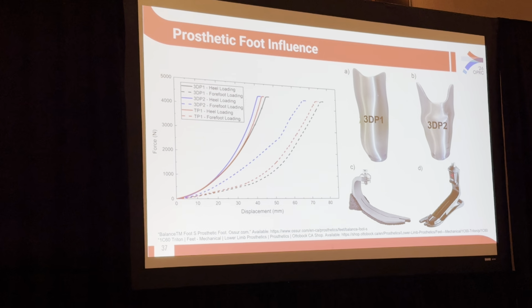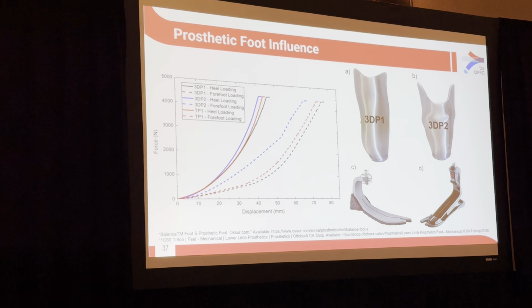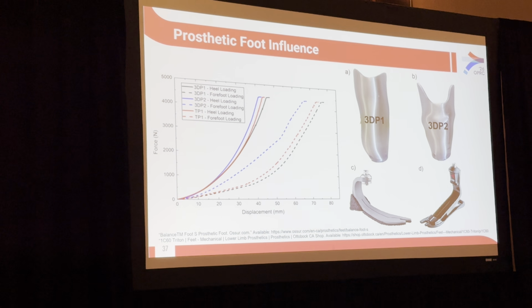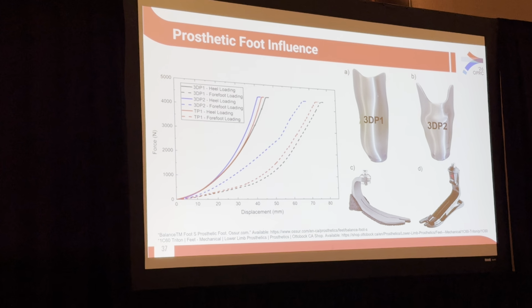Within that standard, we use a foot to mount the sample within the machine. We saw within our 3DP2 sample some fractures, but we also used a stiffer foot. And so although there's further analysis to be made on these results, this just highlights that there are different things that impact the structural conditions that a socket is being subject to.